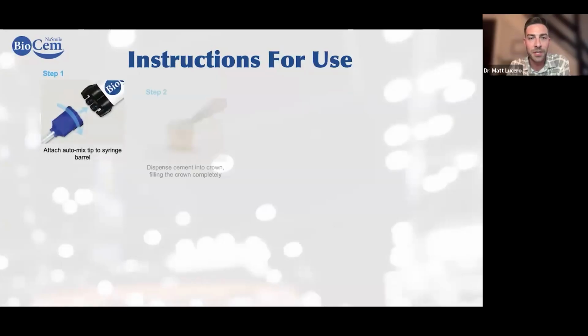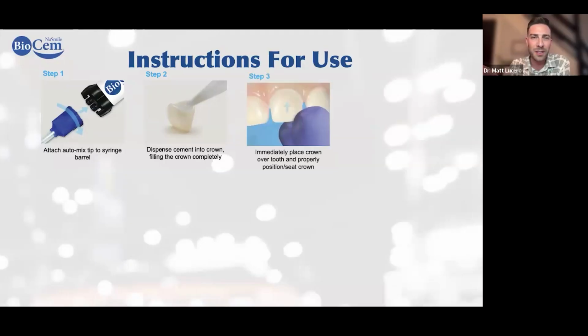So here's the instructions for use with BioCem. It's a little bit different than what you're used to if you're using an RMGI. You'll put your tip on, load up your crown about 2/3 to 3/4 of the way. You want to seat the crown and have a little collar of cement. You can see that little bit of excess right there. With BioCem, it's good to leave that because when we tack cure it, it's really easy to clean up. If you leave it thin and smear it, it's a little harder.